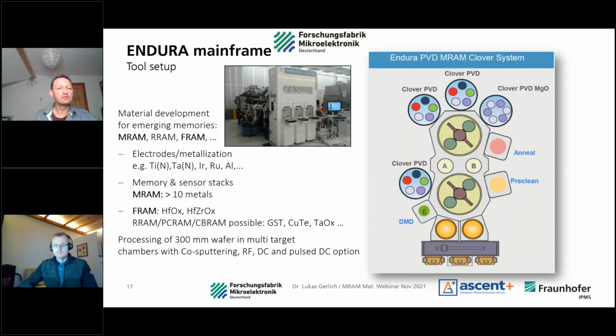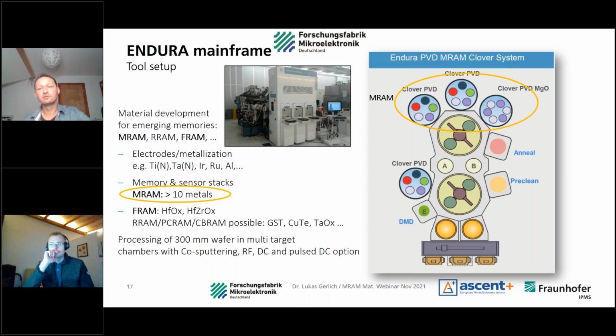The tool is developed for emerging memories, mostly for MRAM, FRAM, and much more. So it can, of course, also deposit electrodes and metallization. But in our case, we use it for memory and sensor stacks. With the MRAM chambers, we can deposit more than 10 metals. It's here on the so-called transfer part of the tool. Here 16 targets can be mounted at once. Mostly you use more than 10 metals. These are typical MRAM metals like cobalt iron boron, cobalt platinum, cobalt tantalum, and much more.